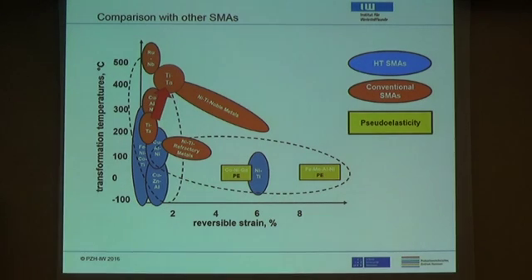So if you compare this new material with what is on the market, here we have transformation temperatures. This is the reversible strain. Then the standard nickel titanium is around here. So you have high strain, but a low transformation temperature. Or you have these other materials that have very high transformation temperatures, but not much strain. And so far the only solution was nickel titanium with lots of noble elements. And with this new titanium tantalum, we were able to move from around here up to here. So we have pretty good temperature capability, and I would say decent strains. And if we induce the strong texturing, then we think we can move in that direction. And then these materials might really make it.